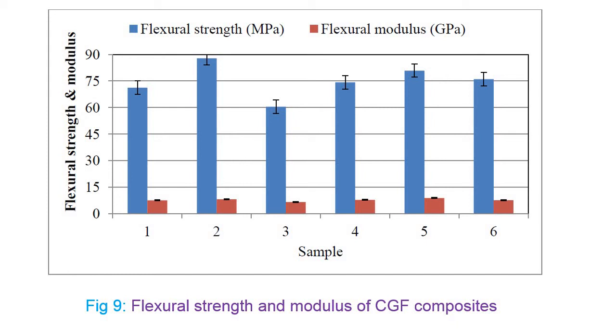Okay, and then flexural modulus, that is in red color, you can see it is in gigapascal. Don't get confused. Flexural strength is in megapascal and flexural modulus is in gigapascal. The flexural modulus is nearly 6.55 gigapascal to 8.86 gigapascal. When we are going for flexural modulus, we will call it bending modulus.